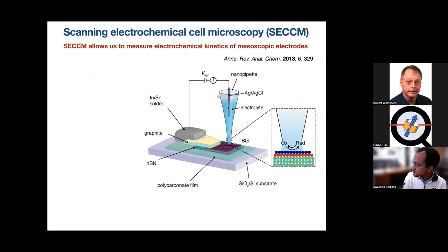but we got there eventually. And so we use a technique called scanning electrochemical cell microscopy, or SECCM, which allows us to measure electrochemical kinetics of mesoscopic electrodes. Basically we pull a capillary, we heat a quartz capillary with a CO2 laser and pull it until it tapers off and breaks, and then it forms a nice little nanopipette at the end with a diameter that we can control from, let's say, 10 to 300 or 500 nanometers or larger. And then we fill that with the electrolyte of interest. A small droplet protrudes from the base of this pipette, and we can use it as a scanning probe, and we can perform electrochemical experiments within this little droplet.